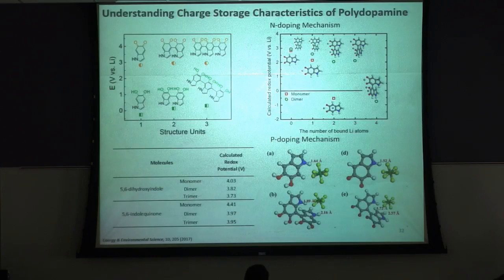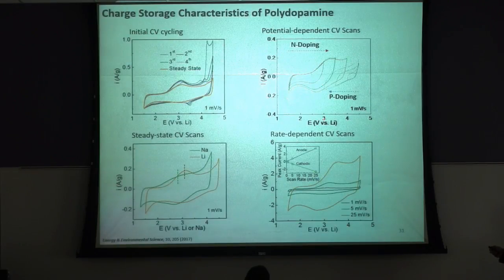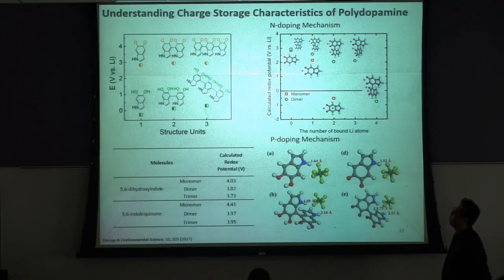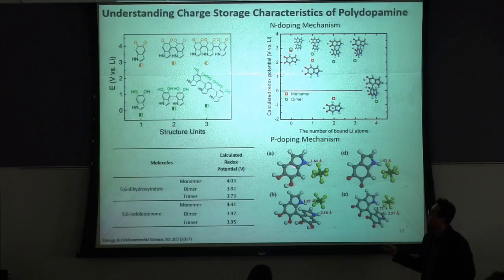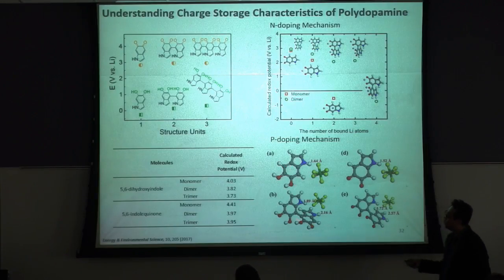Then, again, Professor Seung Woo Lee at MSc calculated the redox potential of this polydopamine film. We calculated the redox potential of this 5,6-indolequinone, which includes this carbonyl group, and also this 5,6-dihydroxyindole, which has this hydroxyl group. As you can see, the calculated redox potential is close to 3 volts, right? So we can see this 5,6-indolequinone is the major contributor to the redox reaction. And this 3 volts is pretty consistent with the electrochemical result. As you can see, we see a huge oxidation and reduction peak at 3 volts. Also, we calculated the redox potential for this p-doping mechanism by considering the interaction between the anions and this monomer, dimer, and trimer.